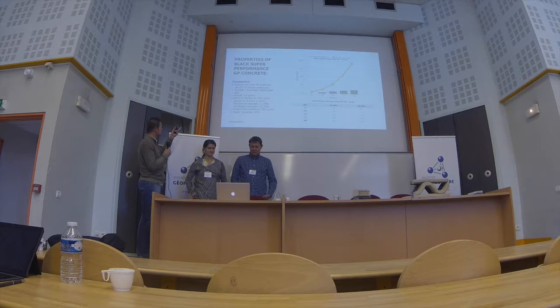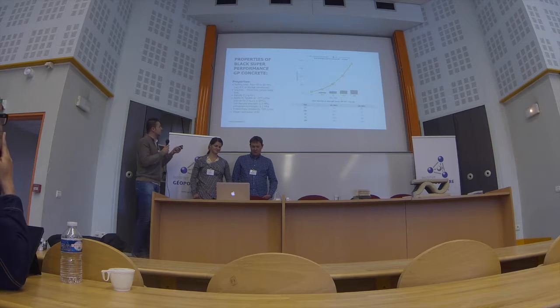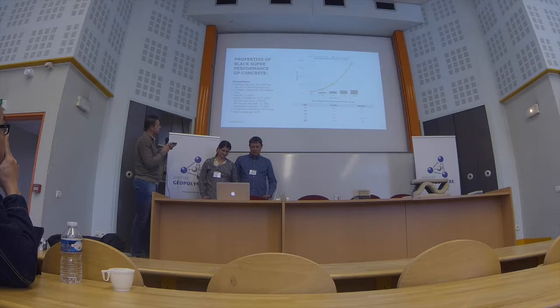I tested and I found 2.3 megapascal of flexural strength and 6.2 of compressive at only 24 hours, so a very good result. Freeze-thaw resistance 500 cycles, Russian norm, and water resistant W18, another Russian norm. And this is the development of mechanical strength in compressive and in flexural.